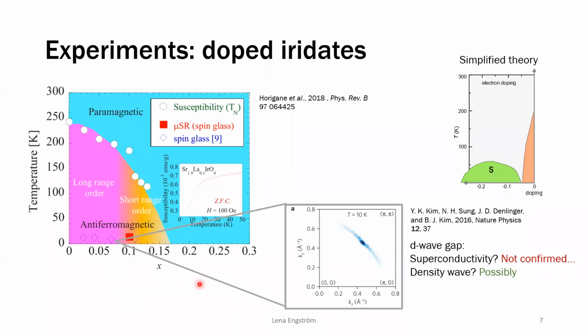So it's mainly speculation. There has been some pseudogap order that people have recognized, which seems to appear, even in this experiment, where they go to higher temperatures and do see some more Fermi arcs. That's also why they thought it was promising that it might be superconductivity. But there aren't too many experiments actually concluding that it is a density wave. It's more the lack of experiments that has been able to reproduce something like this, but stronger, or determining that it is superconductivity at higher strains, higher doping.